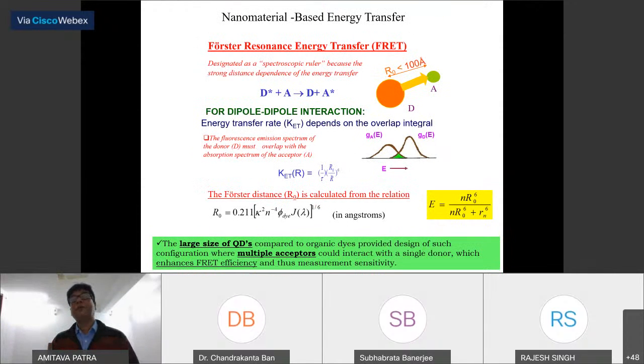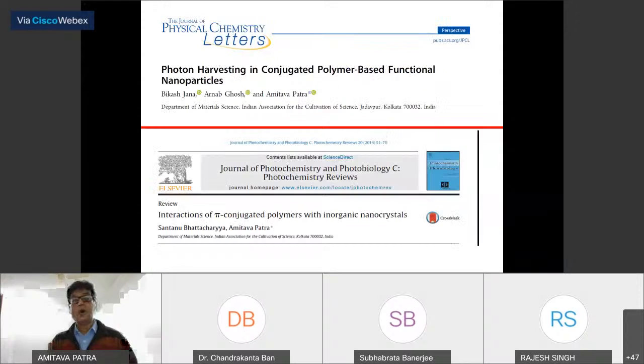So this is the energy transfer process. You have to have an acceptor molecule. When you excite the donor molecule, that energy is transferred to the acceptor molecule, it follows the 1 by r to the power 6. This is called FRET because of the dipole-dipole interaction. In case of nanoparticle, it is very important because of the large size, so it should have multiple acceptors, not 1:1 interaction. That's why number n is there. So if it is a 1:1 interaction, then n is 1. In most of the biological systems, people are using one donor, one acceptor. In that case, n is 1. So in case of nanoparticle, you can enhance the efficiency of energy transfer. These are the papers we reviewed on polymer nanoparticle.